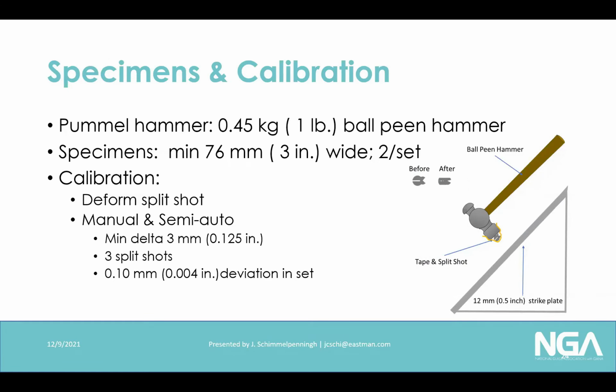You can calibrate the material. It's a simple method. You take literally split shot, tape it to the hammer, as you can see, and you pound it, and you know that you have enough force if it flattens, and you meet the requirements for how hard it flattens. This is a great method for somebody learning how to pummel, to make sure that they have an idea on a manual pummel of how hard they have to strike the hammer. It's an excellent method for the semi-automatic because it tells you whether or not the piston is firing at the right response rate at each time.